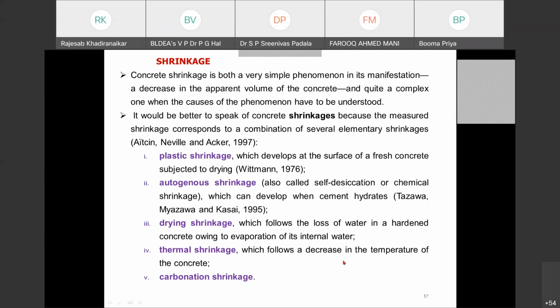Coming to shrinkage, normally the perception is that since we are going in for more cement or binder content, high performance concrete will have higher shrinkage. But that's not true. Concrete shrinkage is a quite complex phenomenon, and Aitcin, Neville and Acker had a detailed study. So we have plastic shrinkage, which develops at the surface of the fresh concrete when it is subjected to surface drying. Autogenous shrinkage basically depends on the self-desiccation chemical phenomena. Then drying shrinkage is due to the loss of water in hardened concrete.